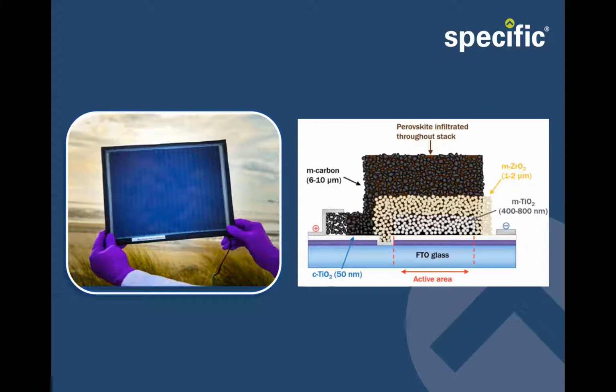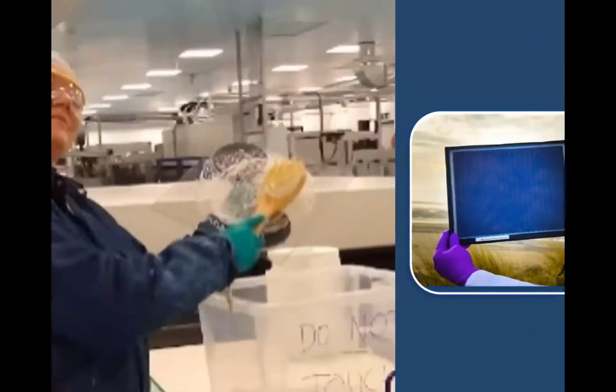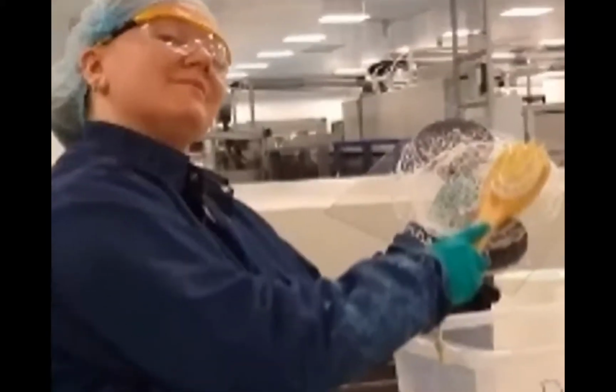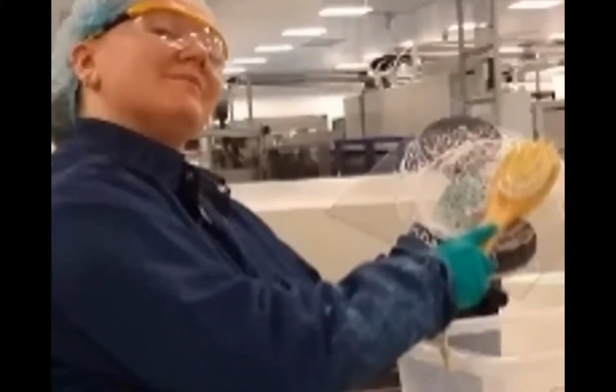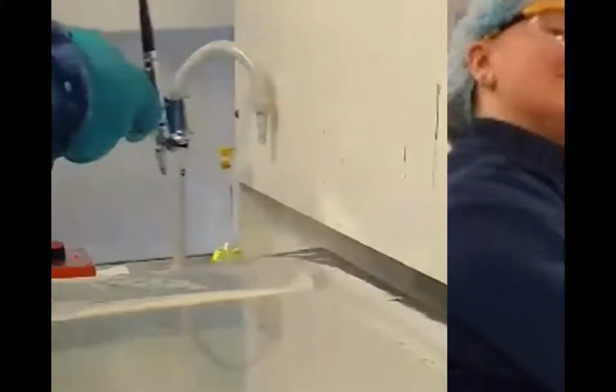To make these, there are multiple steps we have to take. Firstly, the fluorine doped tin oxide coated glass is cleaned with a range of cleaning solutions and solvents. In our case, they are scrubbed by hand, which takes a little bit of a while and is about as fun as doing the washing up for your dishes. But we need this to make sure they are clean enough to make good quality printed solar cells.